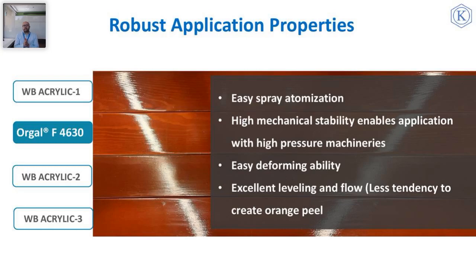I would like to pay your attention to the reflection of fluorescent lamp on the surface. Waterborne acrylic 1 and 3 show much intense orange peel effect, and waterborne acrylic 2 is even worse. It is almost matte appearance after spray. However, Orgal F4630 based top coat clearly has best visual aspect.